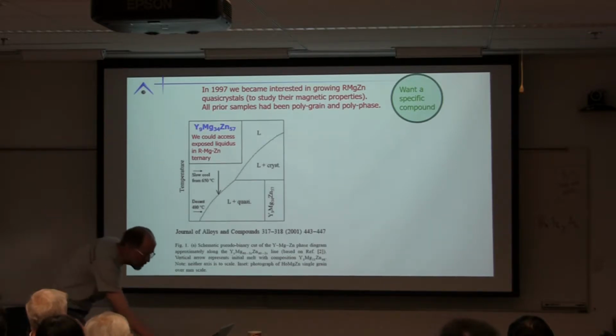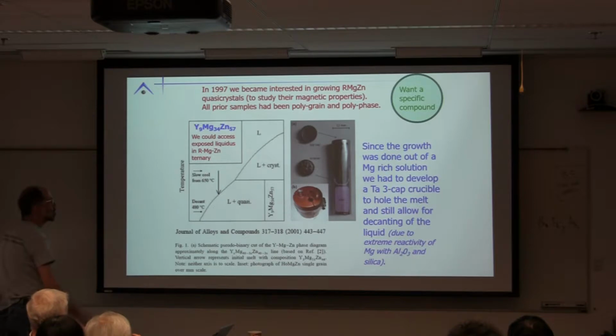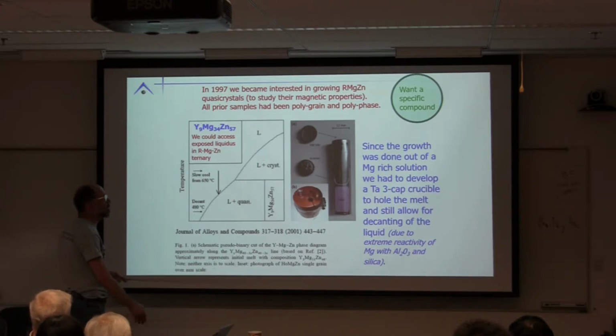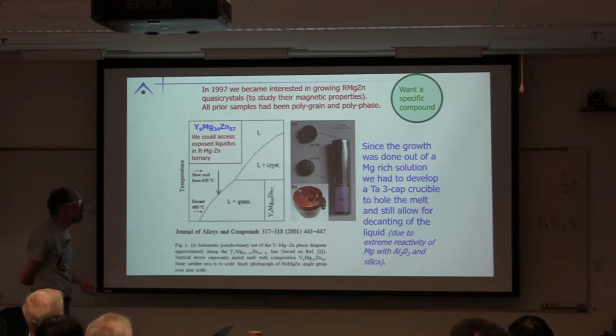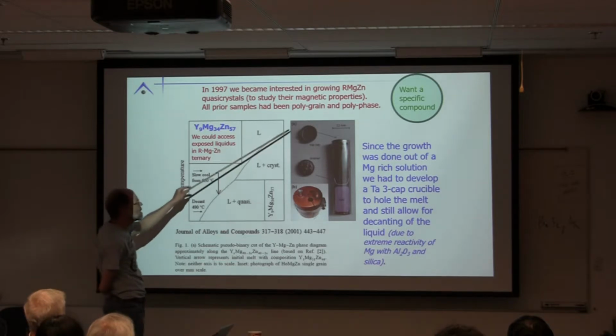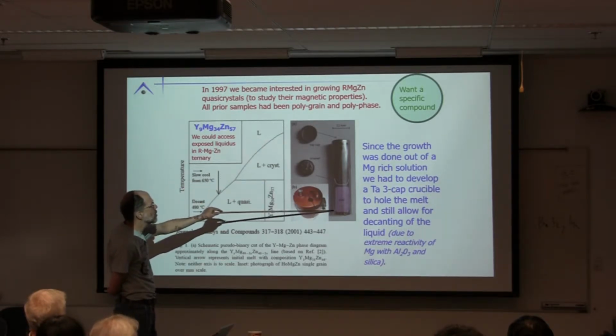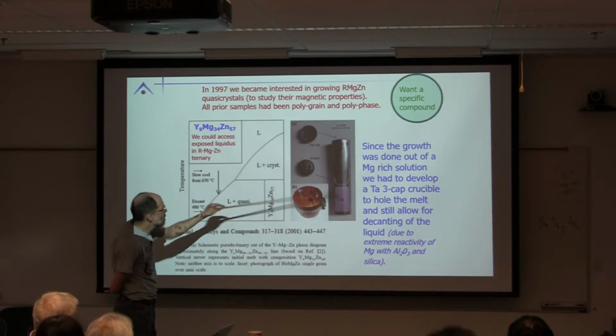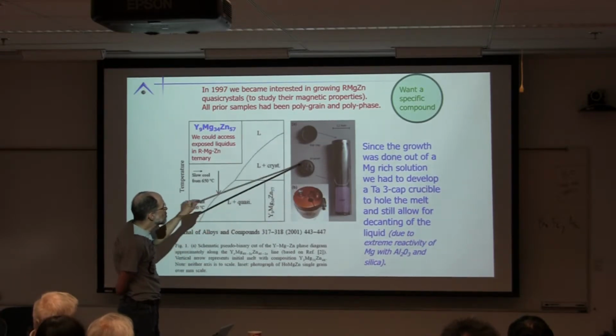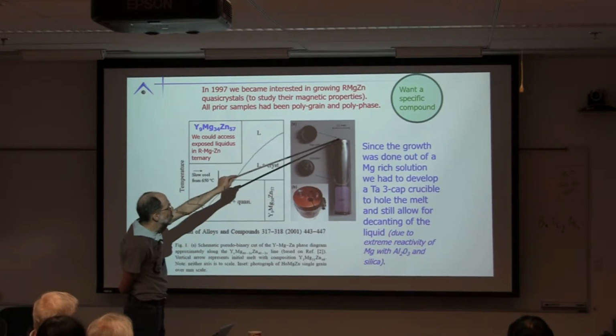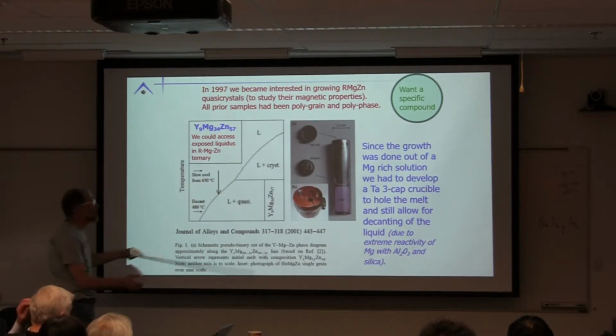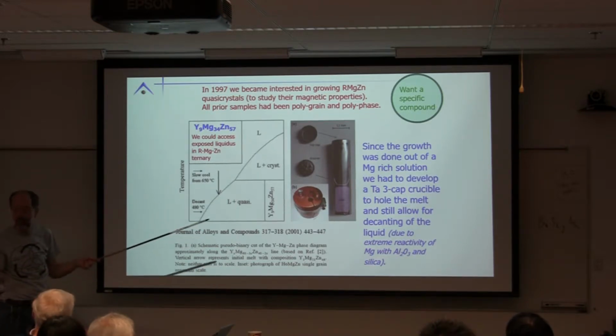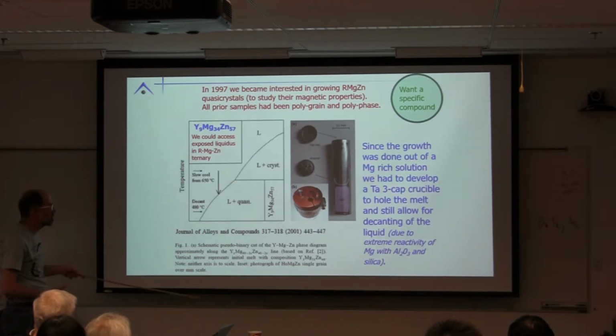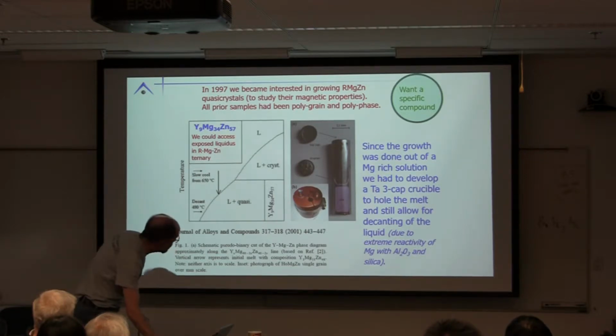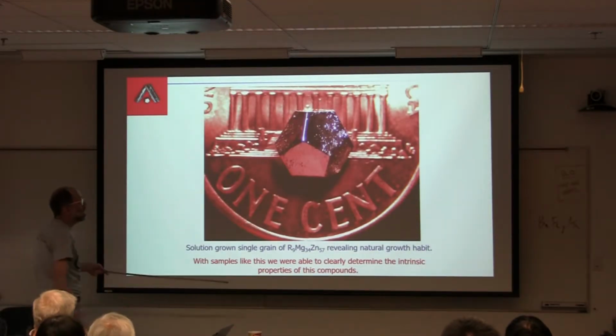Okay? Now, in order to handle this, we needed to devise a way of working with very reactive magnesium-rich solutions. Okay? So instead of using alumina, we had to shift to tantalum, and since we like to decant, we came up with something we called a 3-cap crucible. Okay? So a tantalum tube, we can make these caps nicely, weld them in the bottom, drill holes in the middle one, clamp it in, and then weld this in, and then seal this in silica. And this allows us to grow and decant, as you've gone over with the flux growth already, okay, in a tantalum vessel.